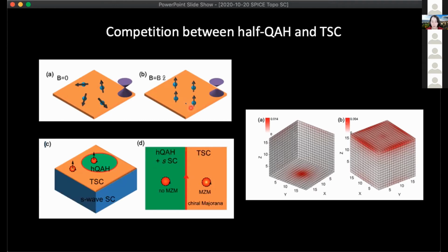So then what we have envisioned is that on the surface of FeSeTe, there will be two types of regions that are bordering each other. One is half quantum anomalous Hall, where your Dirac surface state, before getting a chance to be a superconductor, just got gapped out because of the exchange field. And the other is the superconductivity gapping the Dirac surface state. Now, these are two distinct topological states that can fight for the surface state. And therefore, at the boundary, there will be an edge mode.